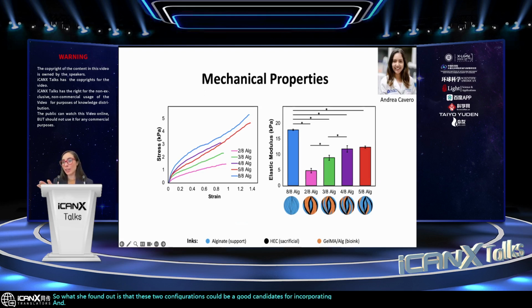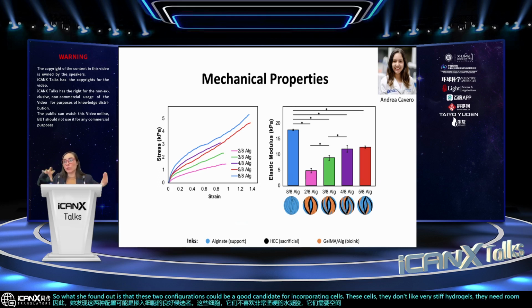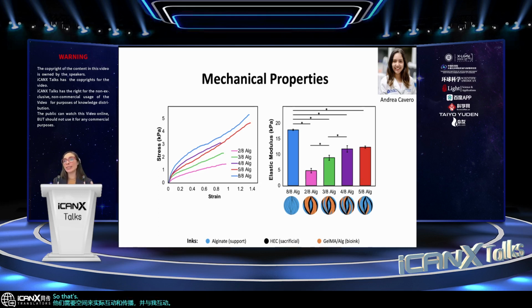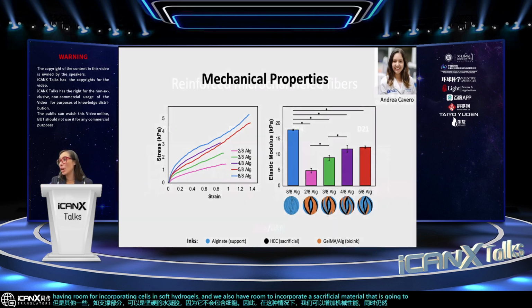The cells, they don't like very stiff hydrogels. They need room, they need the space to actually interact and to spread and to have interaction with neighbor cells. So that's why sometimes these hydrogels might be very weak, but some others, like the support portion, can be a stiff hydrogel because it's not going to contain cells. So in this case, we can increase the mechanical properties while still having room for incorporating cells in soft hydrogels. And we also have room to incorporate a sacrificial material that is going to leave the hollow microchannels inside.